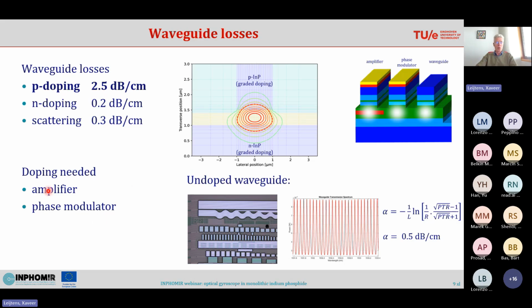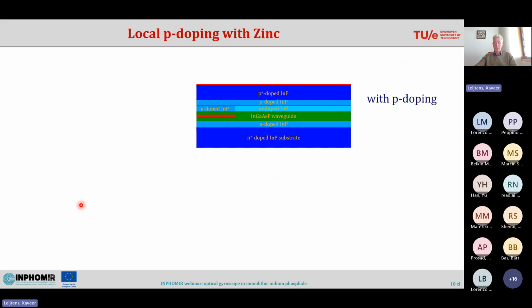But we do need the doping for the amplifier and the phase modulator and the detector. So what we try to do is to make a local doping only where we need it and have the waveguides without doping. So this is the standard way of making the structures with p-doping already in the growth.